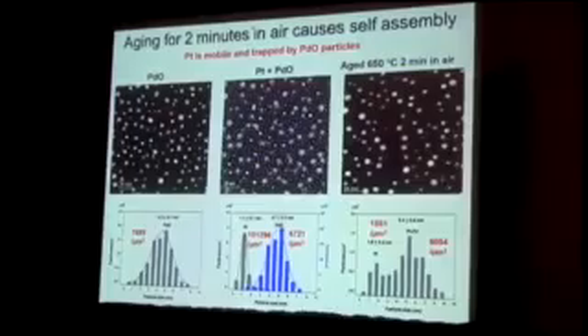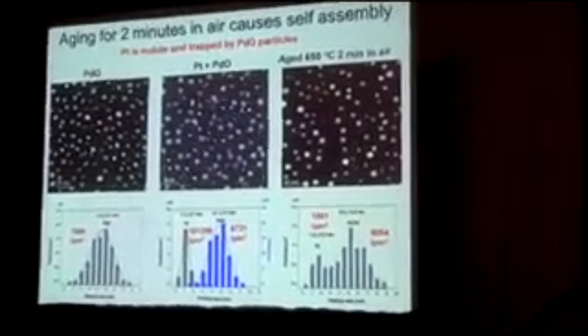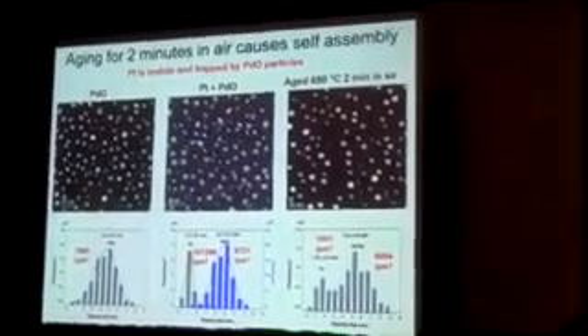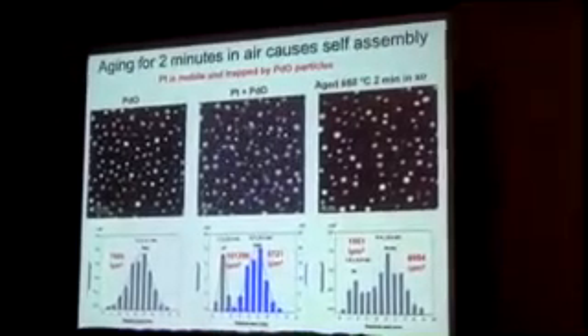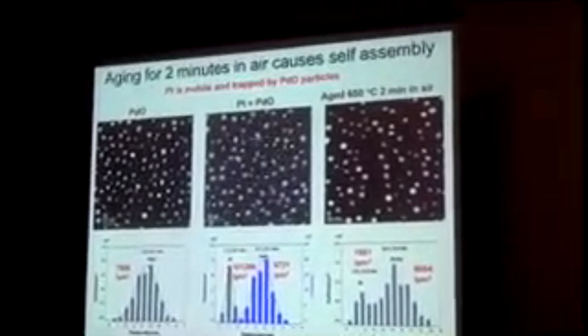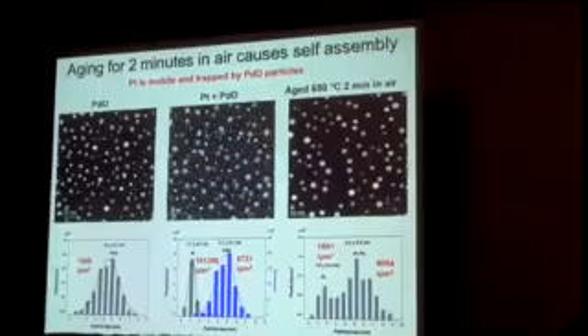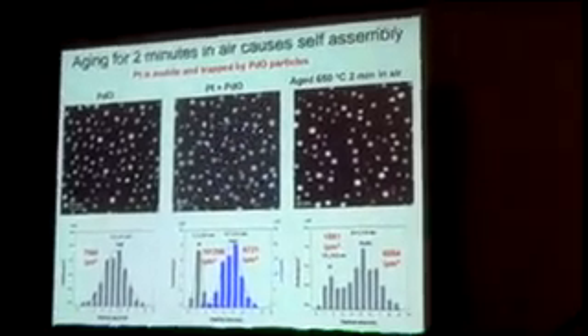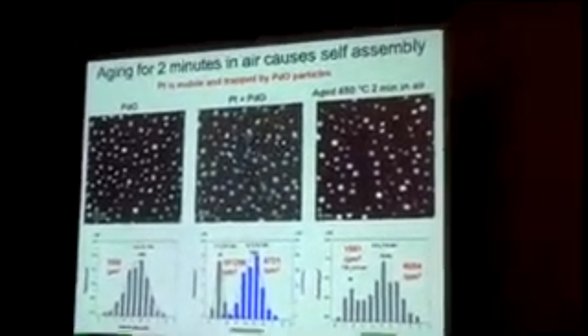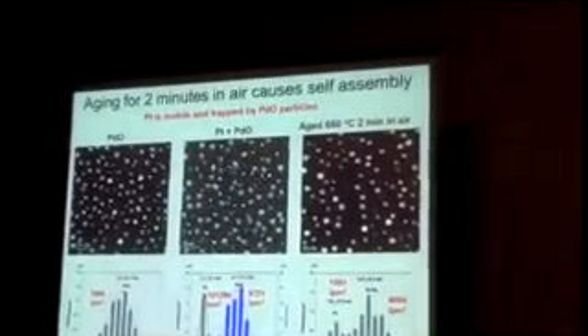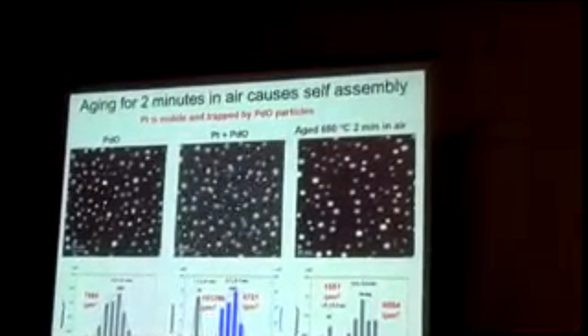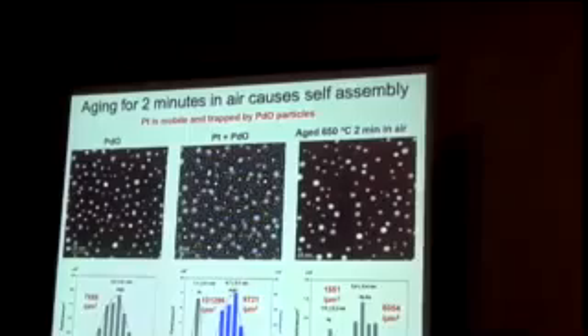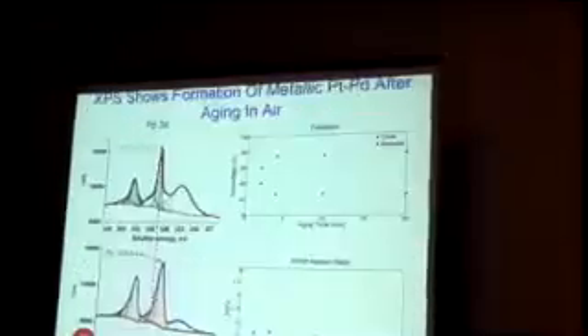And we see that change in particle size distributions, that large piece of platinum is gone. So this is the origin of self-assembly. The self-assembly of platinum palladium catalysts involves a mobile platinum species that reacts with palladium oxide, reduces it, and then becomes platinum. So it's a self-healing process in the real volume of catalyst.